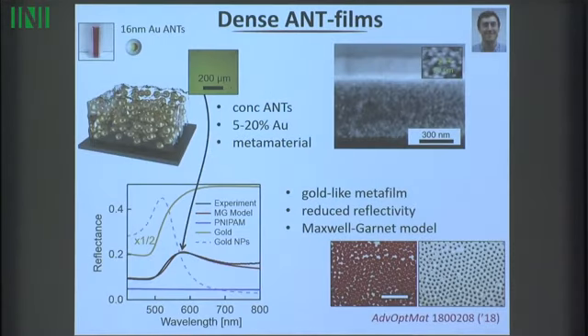Maybe the other thing I should say, so we can do this sort of thing reversibly. This is actually the individual particles in little droplets. These are about 50 microns across, and they're red, just like stained glass can be red, because they're scattering out the green light here. And if I heat them slightly, what happens is all of those condense together, and actually I get this effect where the centers are now black and the rest of it is transmitting light. It's a biomimetic analog of things like squid or octopus, and that's how they change their color. They take dye-based color and they quench it all together, or they make it go further apart. That's how they try and do that. So that's what we're trying to do here.